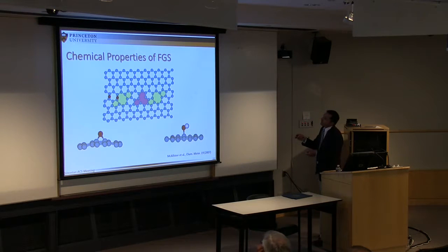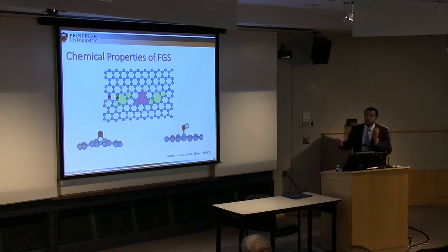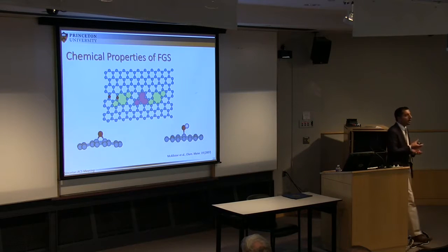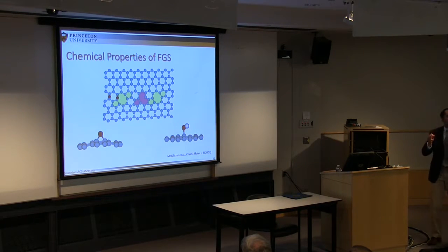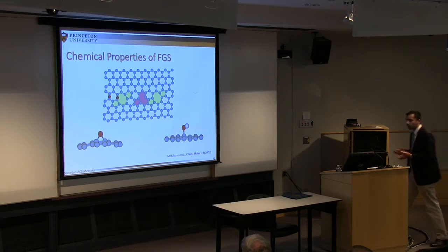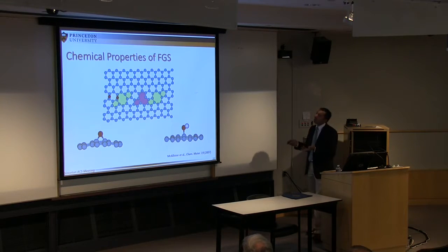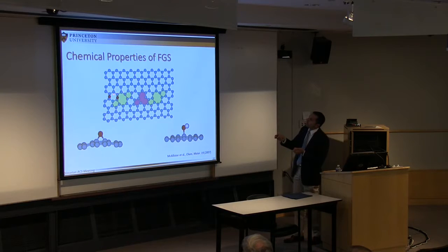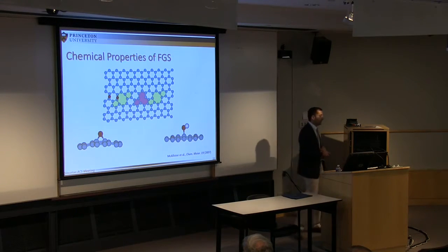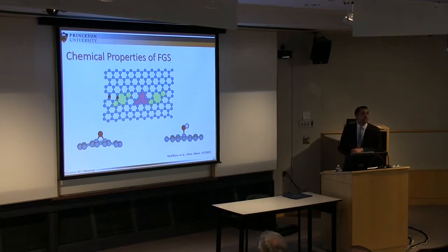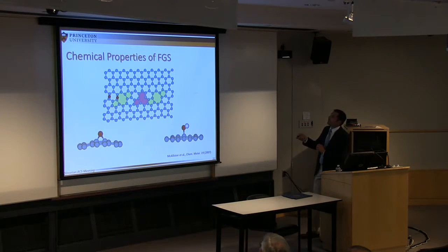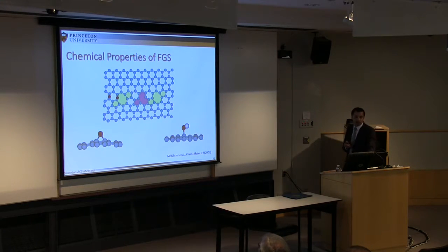And also of importance here is, because the process itself is a highly energetic process, you lose some carbon, and the splitting of the graphene layers actually is coming from the fact that you have CO2 built up. So as you are releasing CO2, what happens, you have some vacancies here. So as you can see here, we are losing carbon atoms. And it gives you these big holes in the basal plane of the material. Okay, so we have functional groups and we have defects.